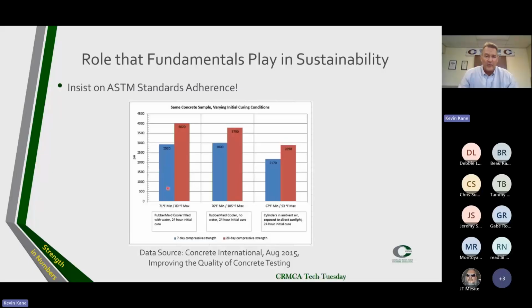If we take a look at this study that we did back in 2014, this was a CRMCA test fest event that we did in Grand Junction, Colorado. This is 3 sets of cylinders cast from the same sample of concrete, and we varied the initial curing conditions. The first set of cylinders was put in a Rubbermaid cooler filled with water. Not very scientific. A Rubbermaid cooler that you could, at that time, have bought from Walmart for 20 bucks. You fill it with water, you put your cylinders in there, and you measure your min-max, and this is well within the specification limit of 60 to 80 degrees. And this is the resulting compressive strength of the properly initially cured test specimens.